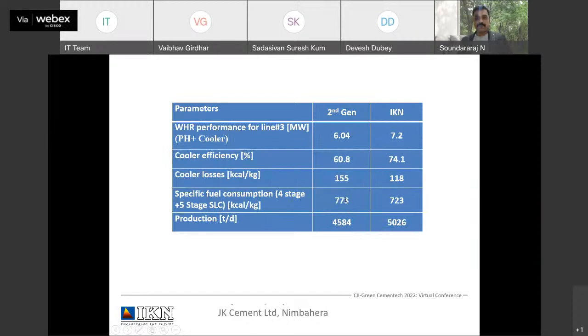If you look at the performance of WHRS, earlier with the second generation hybrid cooler, it was 6 megawatt, and after IKN with hot air recirculation, it becomes 7.2. The efficiency improved by 14% and cooler losses by 35 kilocalories, and heat consumption came down by 50 kilocalories with the help of burner modification also. Production has gone up by 500 tons. The kiln is now operating at 6,500 with the upgraded preheater and still with the same cooler, without any additional capex on the cooler.